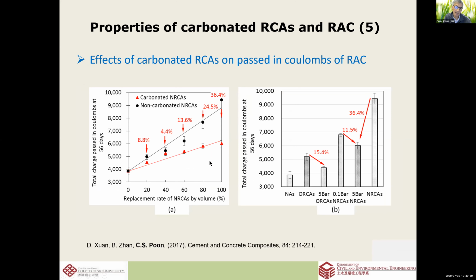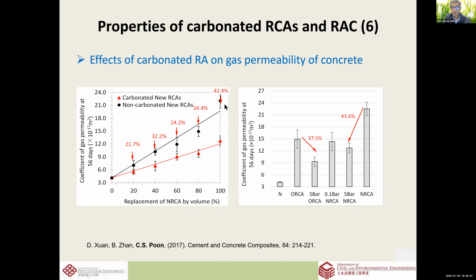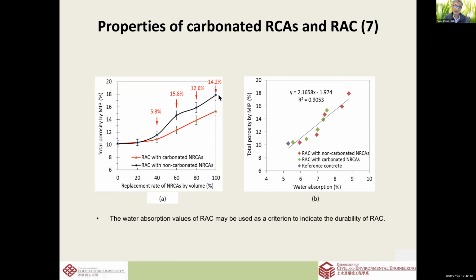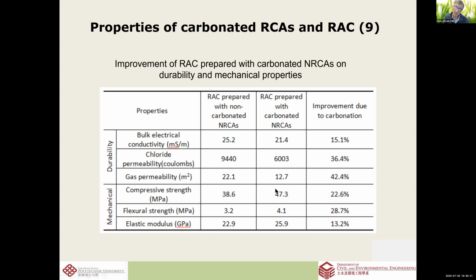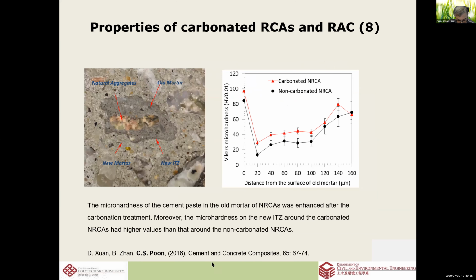For durability, this is about the chloride diffusion, there's about 35% improvement. And the gas permeability is about 42% improvement as well. This is porosity of new concrete, about 14% improvement as well. So in summary, with the use of carbonated recycled aggregate, we can have some improvement in strength and improvement in durability, particularly. So this is of particular interest, and this is quite a highly cited material.